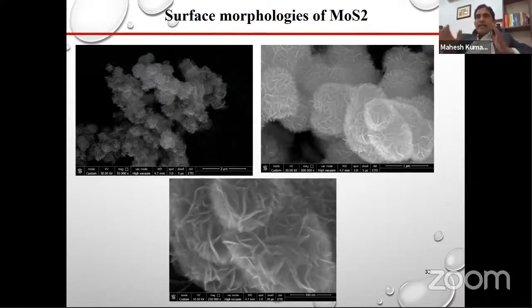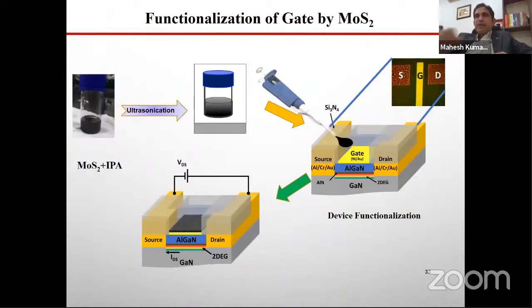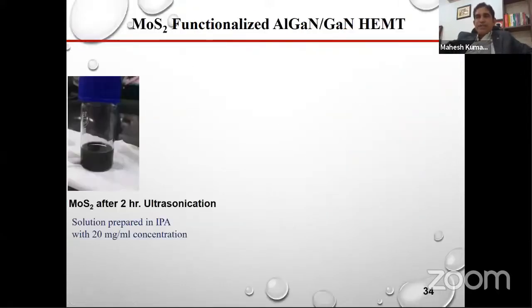Another target is there. Individually we have fabricated the HEMT, and also we have synthesized MoS2. Next we have transferred this MoS2 onto the gate. By ultrasonication in IPA we have dispersed it, and then by the drop cast method we have functionalized this gate. Here you can see a few more images. We have used around 20 milligram per ml of IPA.